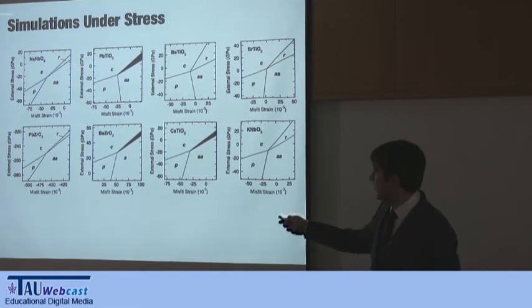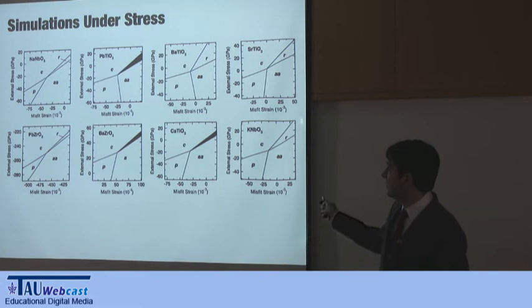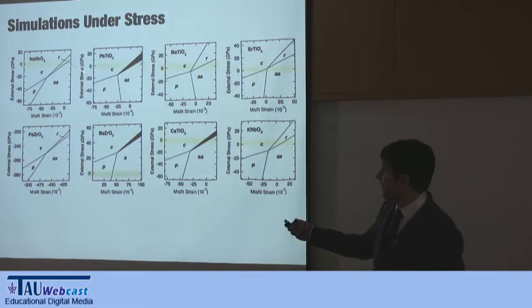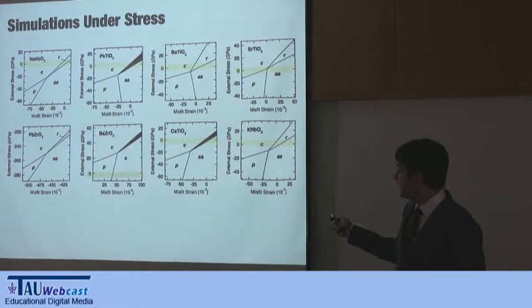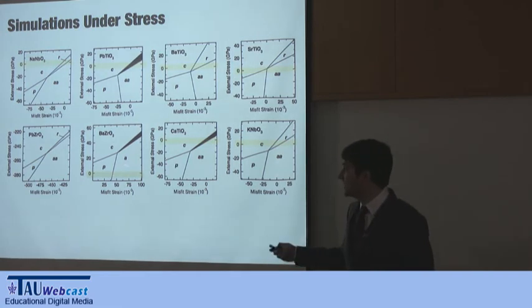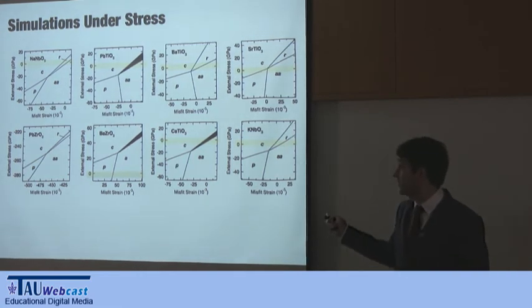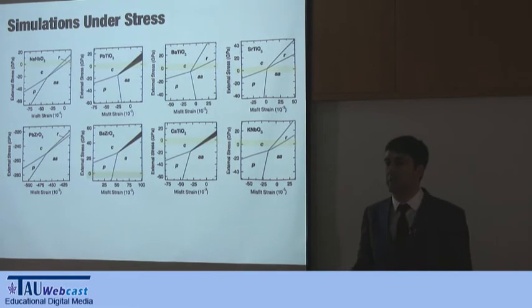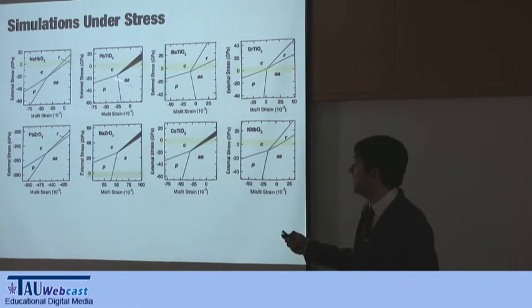So in this case, what we find is that there are 8 perovskites here that in principle show very different properties when you grow them as a film. This corresponds to the 0 stress. But if you use this kind of approach and you look from further, what you can see is that the phase diagrams are very similar. What you find then in real life is that the stress corresponds to different positions.